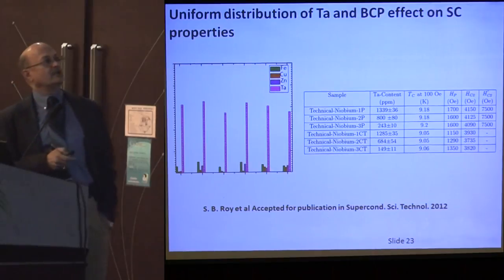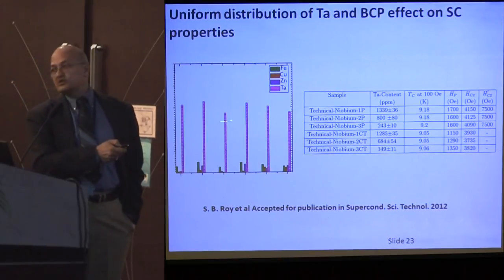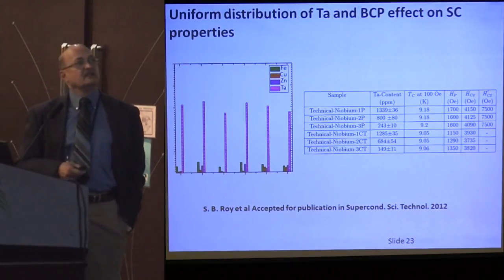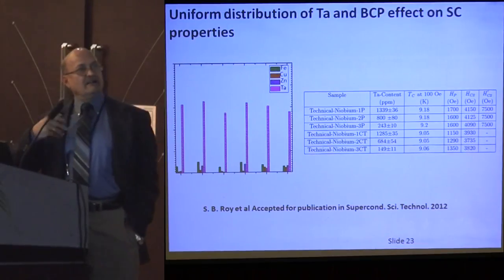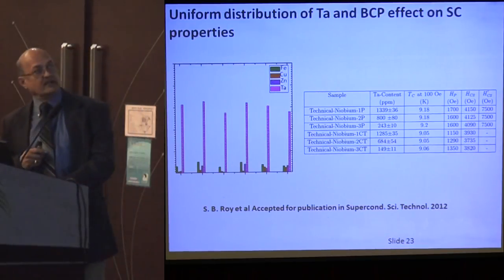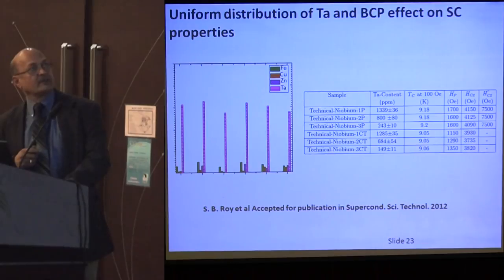We have also done some studies on how uniformly this tantalum is distributed in this SC surface of this niobium. We found that it is very uniformly distributed, so there is no issue of having precipitates anywhere to give bad performance.